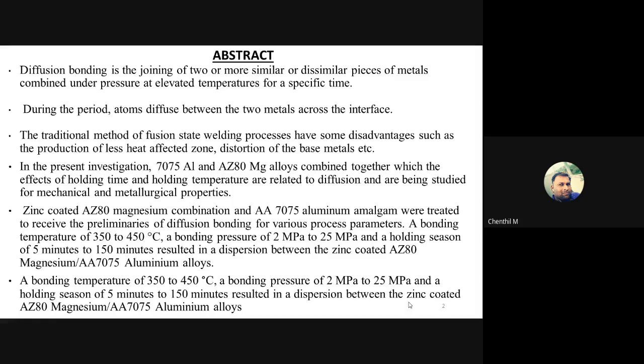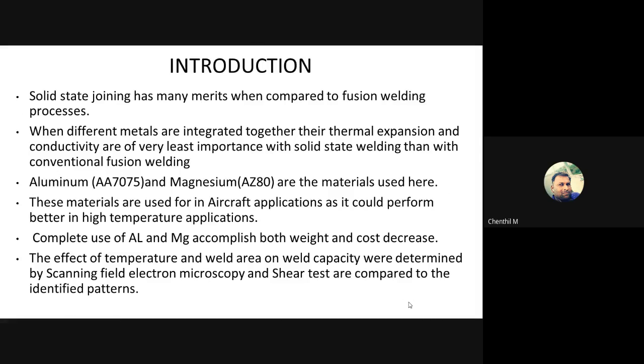After the experiment, with a temperature of 350 to 450 degrees Celsius and a bonding pressure of 2 megapascal to 25 megapascal, we obtained diffusion between the zinc coated magnesium and aluminum alloy. Next is the introduction. What is diffusion bonding? It is a solid state welding process.